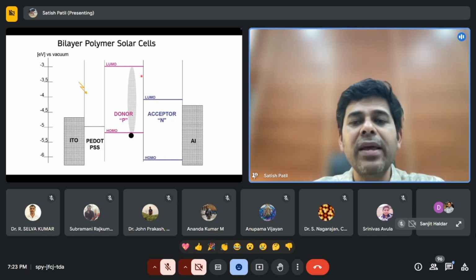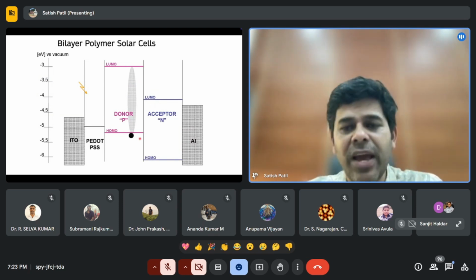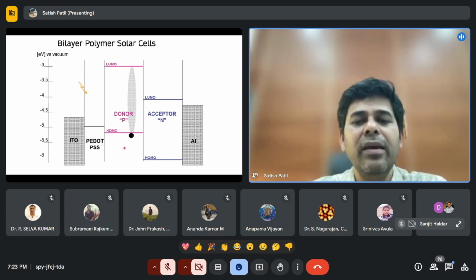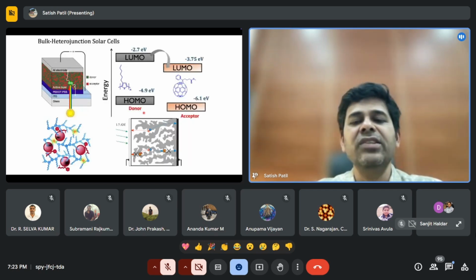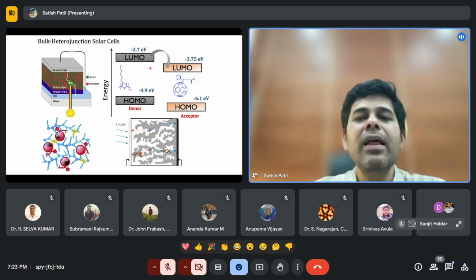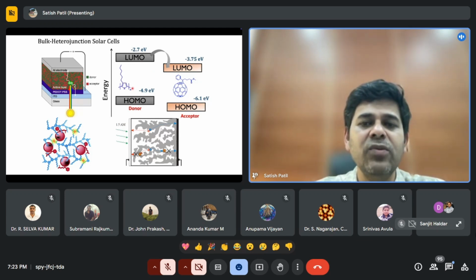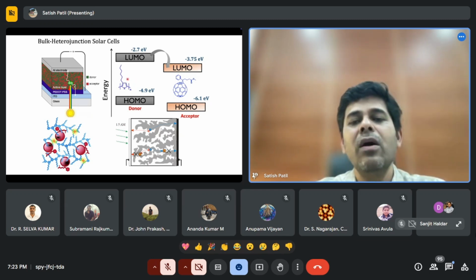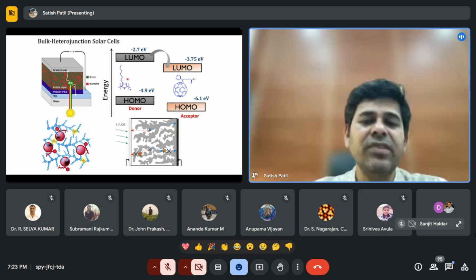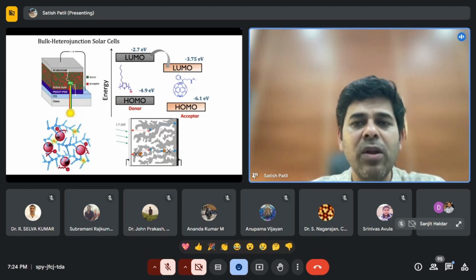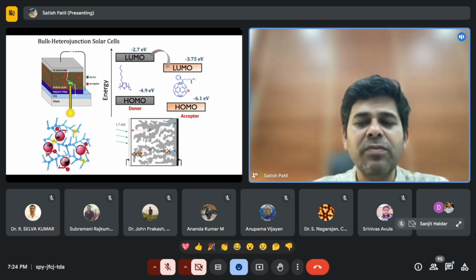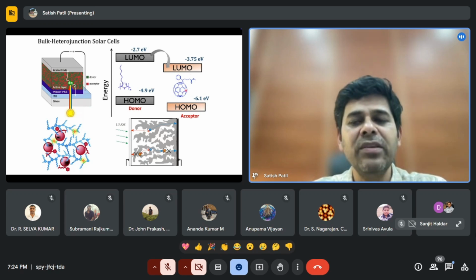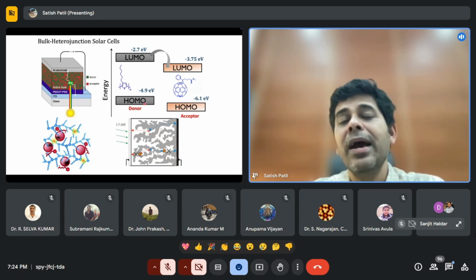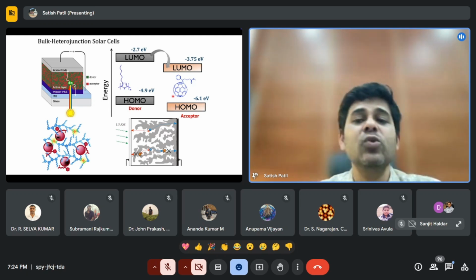Bilayer, they do work because in a bilayer you can separate the charge carriers, but they do not give very high efficiency solar cells because of competitive recombination pathways in bilayer solar cells. Whereas bulk heterojunction, this is the energy level diagram. You see they work very well. And today people make bulk heterojunction solar cells by using P3HT kind of a P-type polymer, or a very well advanced donor-acceptor based polymer like PM6, with non-fullerene material, because PCBM does not participate in the light harvesting mechanism. People use non-fullerene organic semiconductor and make highly efficient solar cells.